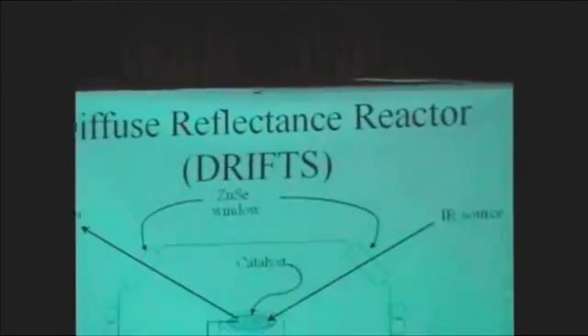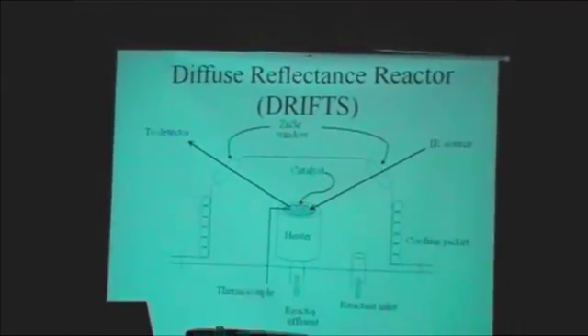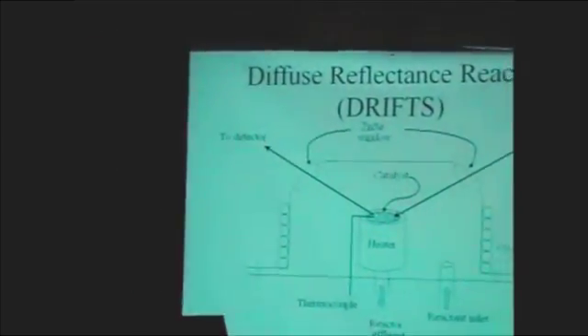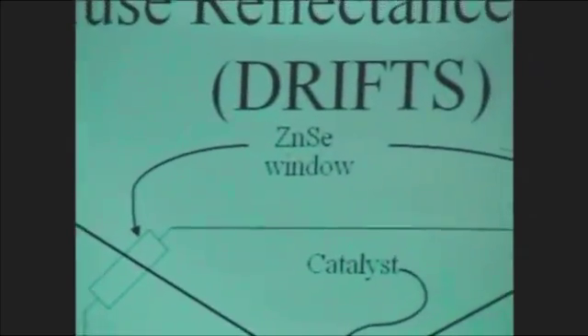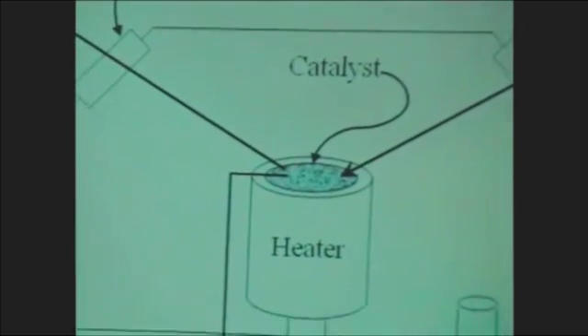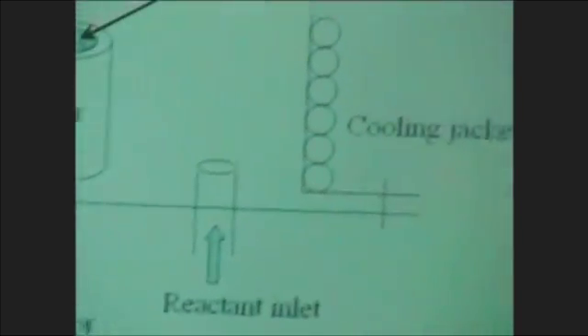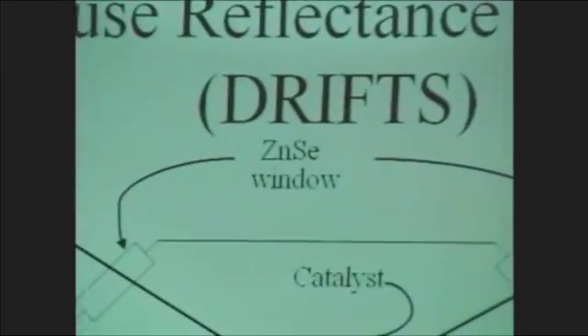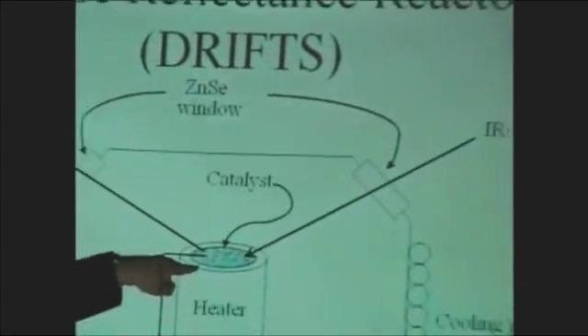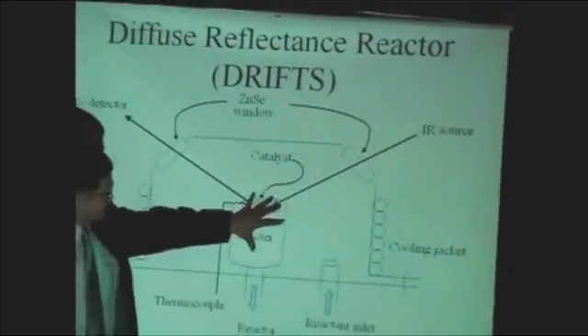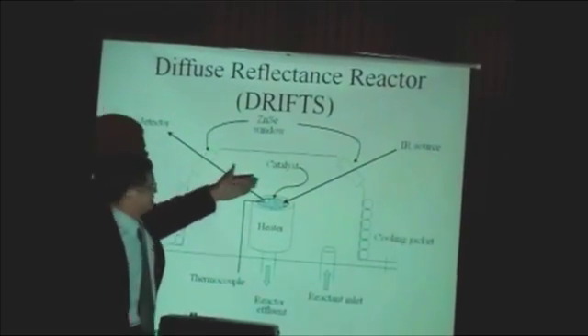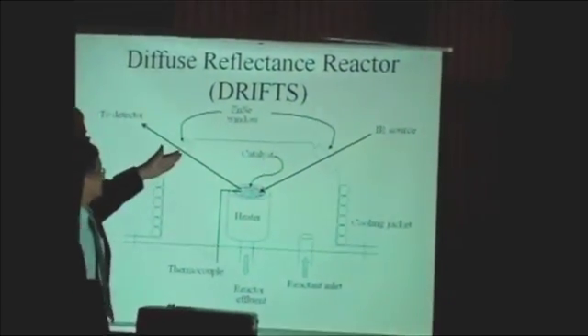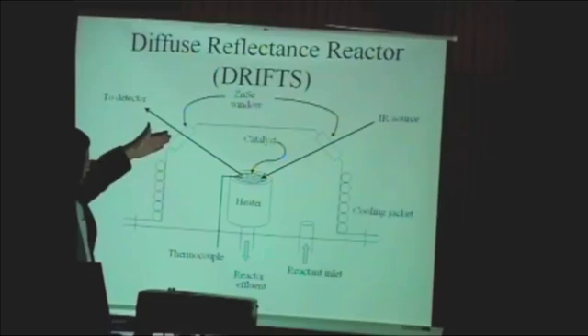We use diffuse reflectance spectroscopy here. This is a commercial reactor cell, and students like to use this simply because it is very simple and very easy to operate, and this is very common. A lot of research groups have this kind of diffuse reflectance reactor. The catalyst can be packed in here with about 20 to 30 milligrams. The heater is in the center, and the glass here is cooled by cooling water. So you can consider this a cold wall reactor.